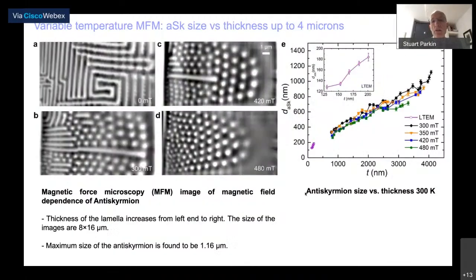And then finally, by varying the magnetic field in the magnetic force microscope, we see now these individual circular objects, and these are antiskyrmions. And I think you can easily see in the image ABCD, on the left, the structure is 100 nanometers thick. On the right, it's 4 microns thick. And I think you can readily see that the size of these circular objects changes from small on the left to big on the right.